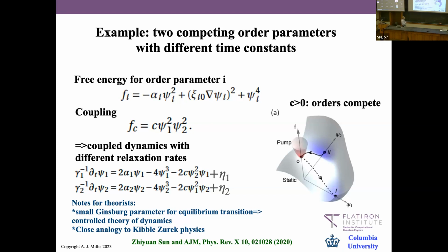So then you have a free energy landscape which looks like what I sketched here. This free energy landscape has one minimum, which is superconducting only, one minimum, which is charge density wave only, and a maximum at 0 in equilibrium. And if the system really wants to be charge density wave, then this minimum is deeper.